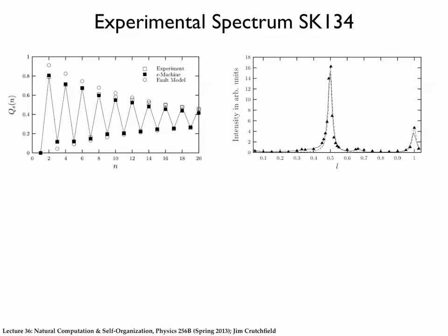Over here, there is a little bit of a broader shoulder, and again, the fault model is kind of missing that, and we really catch that also. So we're really picking up additional structures that have been missing in previous descriptions. We don't do as well over here. It turns out this peak, we don't quite get as well, but we get a fair amount of the structure, as far as looking at the diffraction pattern.